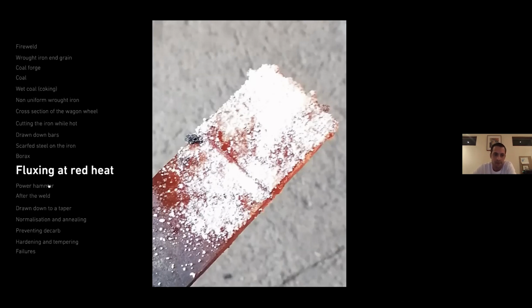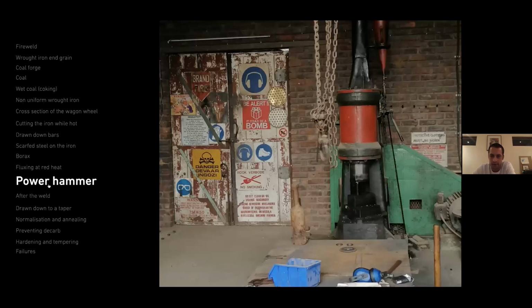I do sometimes use a power hammer. This is my workshop, and it just means that I only have to take 1 heat and bang, it's done. This helps from the point of view of decarburizing the steel, losing carbon to the heat. Every time you heat it up, it sort of diffuses into the air and into the iron. So the less heats I can get it to stick properly, the better. And this helps. But for small irons, it's completely possible. Just do it on the anvil. I'd say 2 to 3 heats would be the maximum for me to make sure the weld is done.